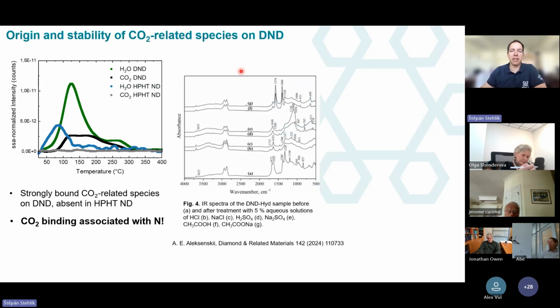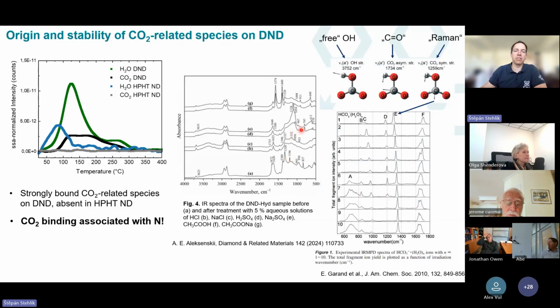So it's obvious that this strong hydration and CO2 binding is associated with the nitrogen in the DNDs. And here I need to take credit to the work of Aleksensky, who actually showed this CO2 capture some time ago already. Well, not that much. And they also made some exchange of the ions. So they proved that, for example, this Raman-like feature is coming from the adsorption of the bicarbonates or hydrated bicarbonates. And this interpretation was based on this nice paper of Garand, where they measured FTIR spectra of hydrated bicarbonate molecules.